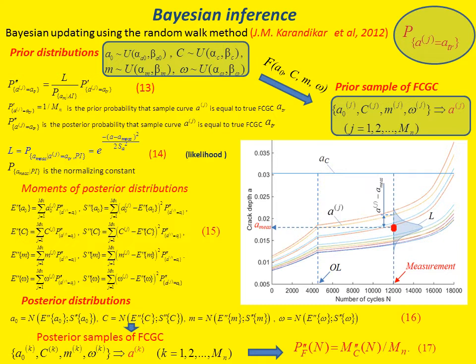In the final part of my presentation, I will briefly describe one of the possible variants of application of Bayesian inference to assessment of the fatigue failure probability. In the work of Jaideep Karandikar and his co-authors, an original approach was proposed that combines Bayesian updating with the random walk method. The key idea of this approach consists in updating the probability of event that a specific sample fatigue crack growth curve is the true or correct fatigue curve.